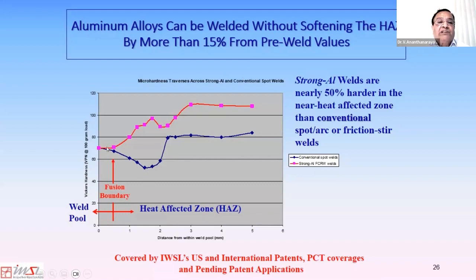And with the focused melt resistance welding, the hardness increases as you come out of the fusion boundary, as the area has not been softened very much. And the heat affected zone micro hardnesses are closer to 85, 90 Vickers. These welds are about 50% harder in the near heat affected zone, and also have similar increase in shear strengths.